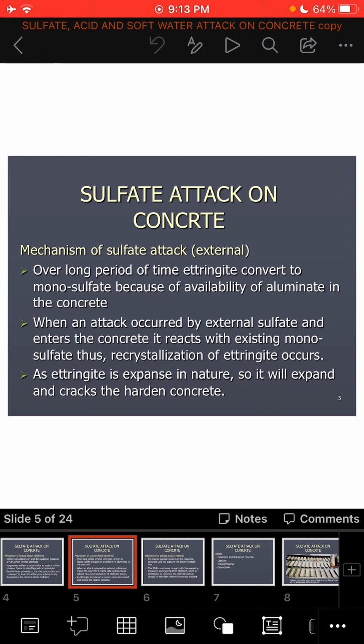When the sulfate attack occurs by external sulfate and it enters the concrete, it reacts with the monosulfate within the concrete that formed from ettringite, and it will start recrystallization of the ettringite. As we know, ettringite is expansive in nature, and it would be so deleterious for the hardened concrete, not for the soft concrete, as it forms in the initial setting time. It will also expand and crack the hardened concrete.